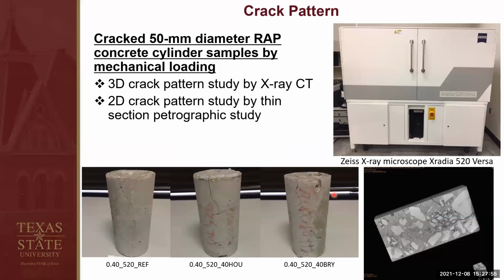We also did some crack pattern analysis. What we did is that we manually cracked the RAP concrete under mechanical loading. Then we put the cracked sample in our X-ray CT. Then we were able to see the internal cracking pattern of the samples without fully breaking the specimen. And we also observed the crack pattern using the thin section specimens under the microscope.